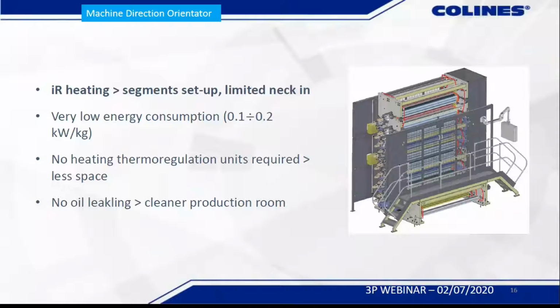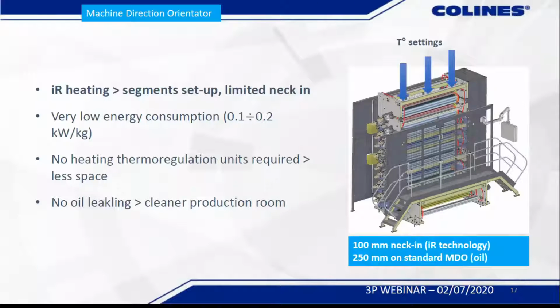So we have segments set up. Basically, we can define up to 5 different zones to hit within the left to right cylinder. And with a special technique, we are able to keep the neck-in very, very small. So we are talking about 50 mm each side, whilst with the standard MDO unit, you go minimum 250 mm